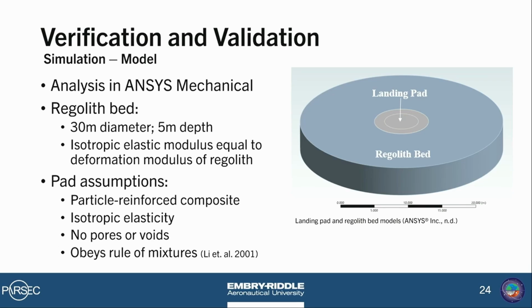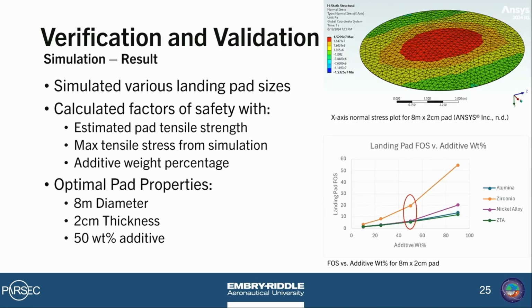For our landing pad, we assume that it is a particle reinforced composite, that it also possesses isotropic elasticity, that no pores, voids, or flaws are present in the landing pad structure, and that it obeys the rule of mixtures, which allows us to estimate a composite elastic modulus and composite tensile strength. So using this calculated composite tensile strength as well as the maximum tensile stress from the simulation, we're able to calculate a factor of safety.